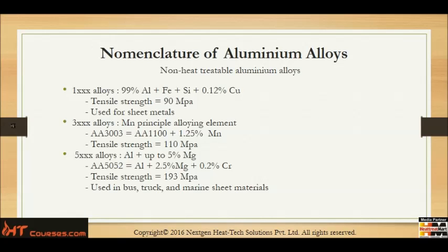Now starts to become a little more descriptive. Starting with the non-heat treatable aluminum alloys, we have the 1XXX series, which is 99% pure aluminum, plus a trace of iron, plus a trace of silicon, plus 0.12% maximum of copper. This has a fairly low tensile strength of 90 megapascals, and it's used principally for sheet metals.